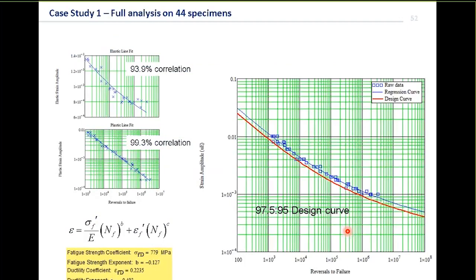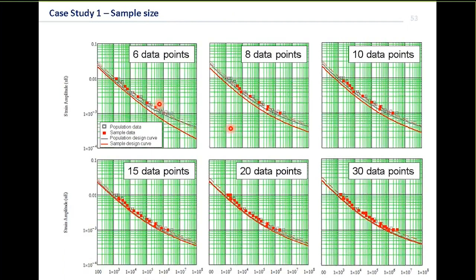So here we can see the full family of 44 data points. You can see the nice fit there. You can see the red line here is that 97.5, 95 design curve. And here you can see the fit through the elastic and the plastic points. Now here you can see what happens when we reduce the number of points. So if we have 6 points, then clearly that is the minimum that we can use to fit 2 straight lines through it. So the design curve here is very low compared to the other one. If you look at it, it's moved quite a lot over because of that.